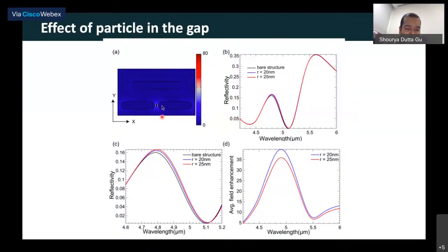Furthermore, if I calculate the field on this particle that is trapped in this gap, what I notice is that the field is enhanced by a factor of around 35, right? So what this is telling me is the IR absorption signal will be enhanced by a factor of 35 squared, which is around 900 times higher as compared to without these structures, right? So that is what we were interested in doing. And so this tells us that you can actually apply the concept that we had used before, that of trapping and sensing, even in the case of IR absorption. It is not just limited to the case of Raman scattering.